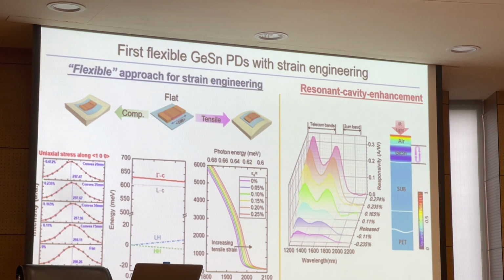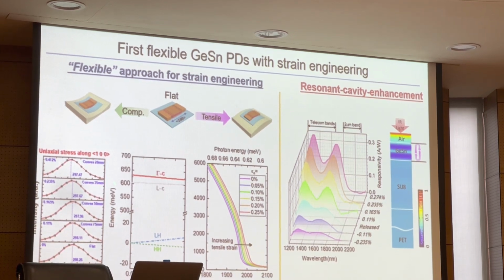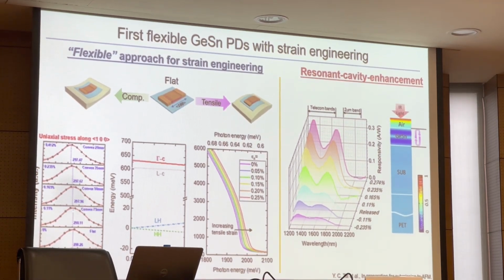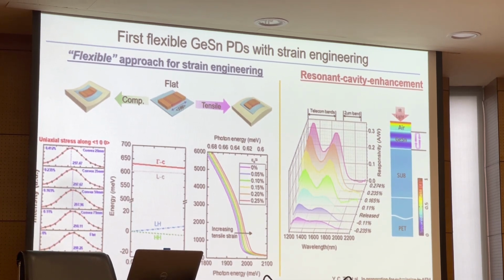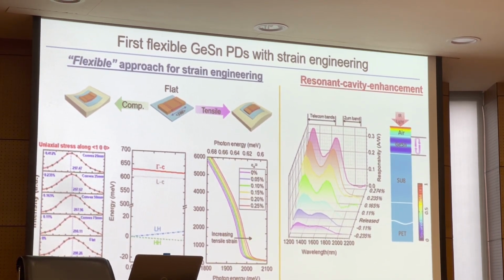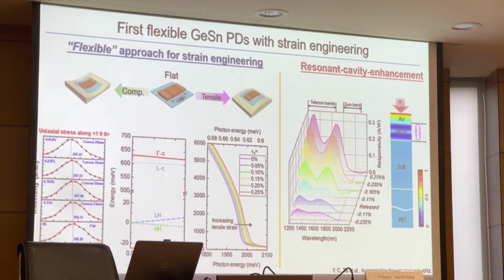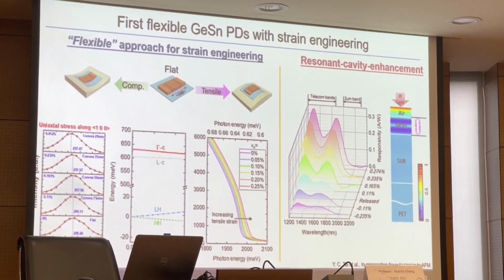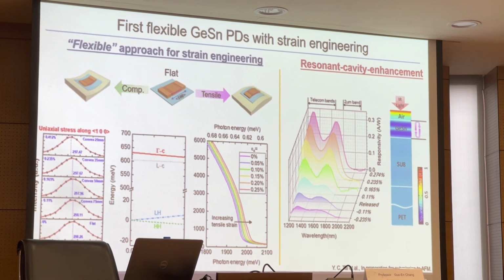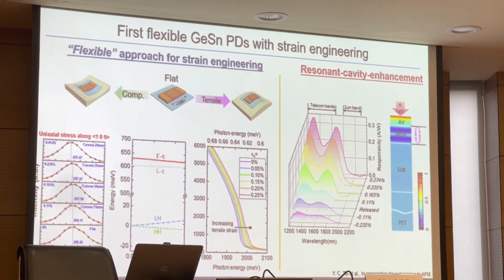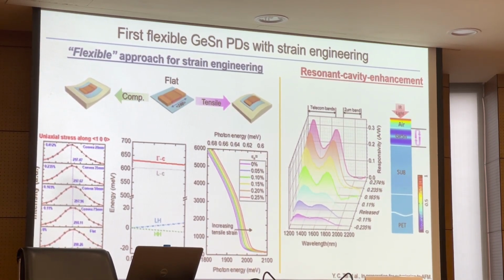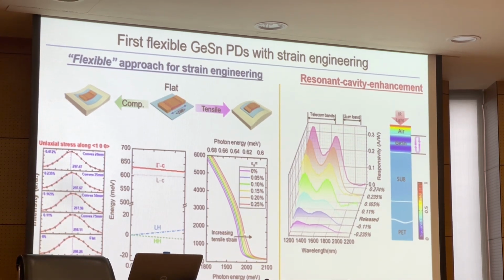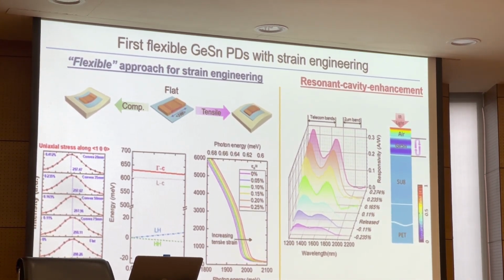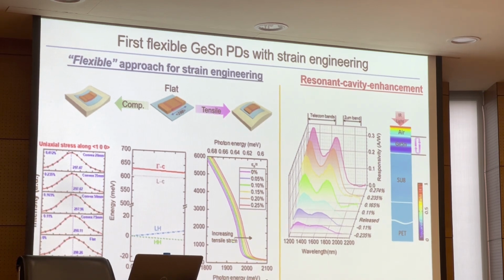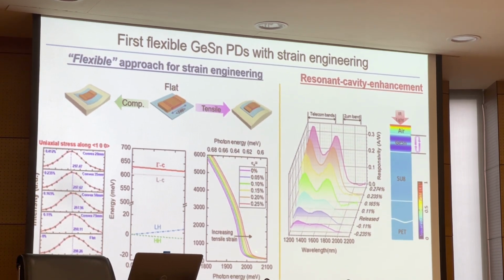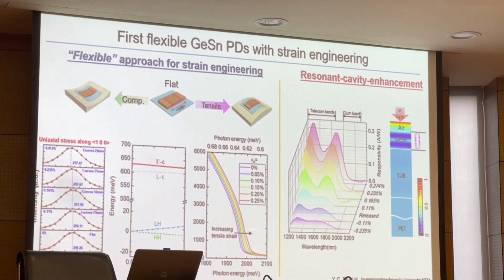From the Raman experiment, we can see that when we bend the sample with different radii, we can clearly see a Raman shift, which means strain has been introduced into the germanium film. From our calculation, we can also see that when we bend the sample, the absorption coefficient spectrum shifts to longer wavelengths.